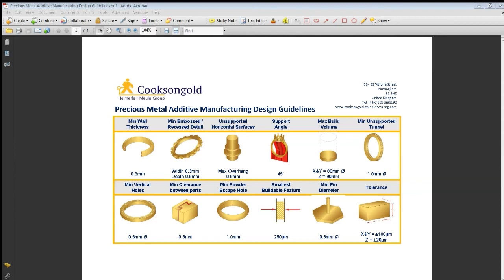The smallest buildable feature is 250 microns. The minimum pin diameter is 0.8 millimeters. If the pin and the wire is too thin, it will struggle to stay straight during the build, as although it won't be touched, there is a moving part in the printer that can disrupt any part of the build. And the tolerance is 100 microns for the X and Y axis, and then 20 microns for your Z axis. So if you want to have a look at building a larger part that goes on the platform, please keep that in mind. That's brilliant.